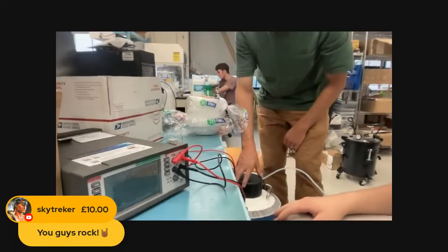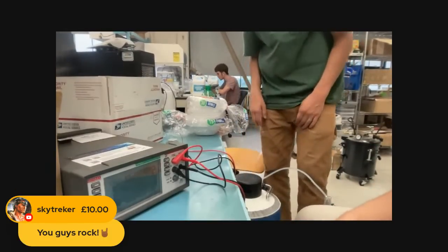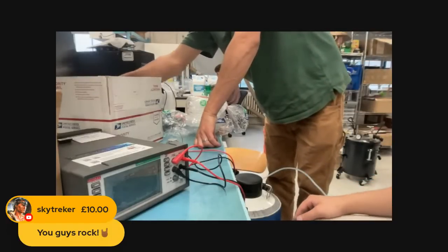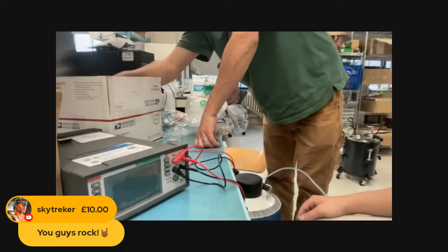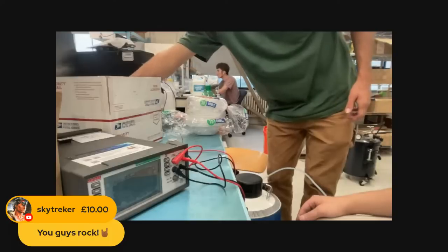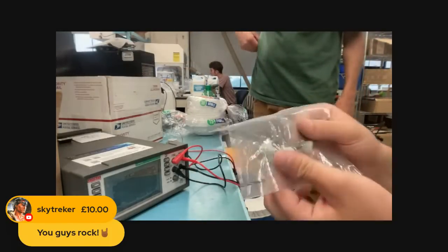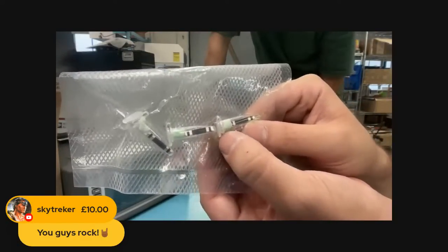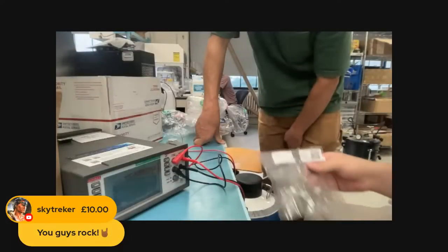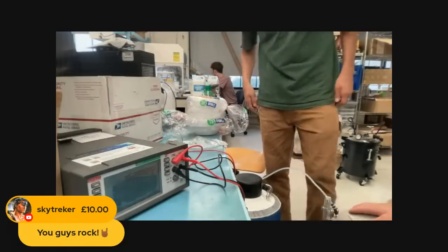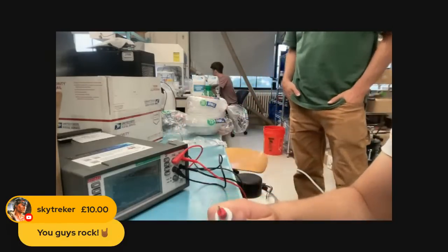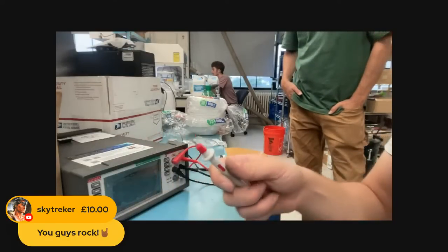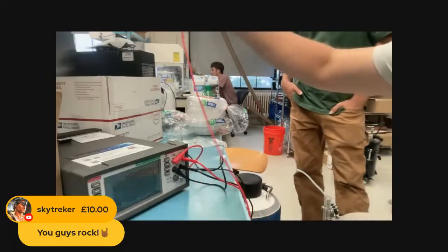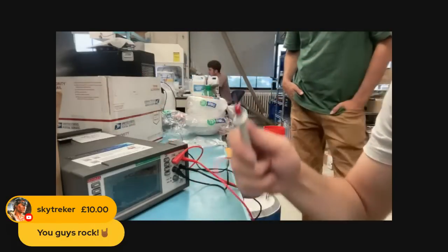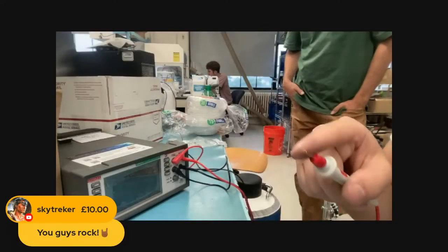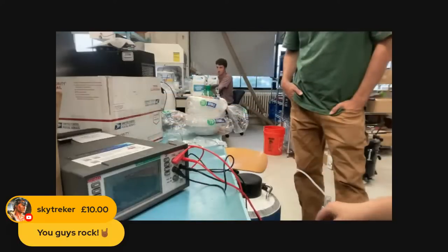Oh yeah. We have liquid nitrogen down there, and we want that to last the week, hopefully. Yeah. But we had these sample superconductor YBCOs so that we could test probes. So right here, the test probes that we got. Yeah. So these have silver attachment points for 4-point probing, and we'll get an actual 4-point probe and we'll test it with that, because these normal probe tips are not good enough to test superconductivity. They're nickel plated. You really need gold plated tips to test superconductivity well. And these aren't even the right type. You can get really good 4-point probes that have 2 tips in one of these devices, and then you just have 2 instead of 4, and they're a lot easier to handle.